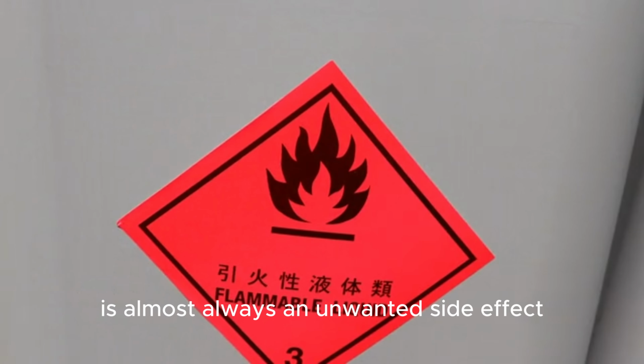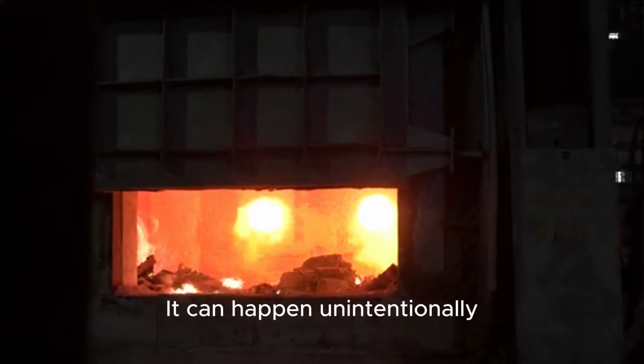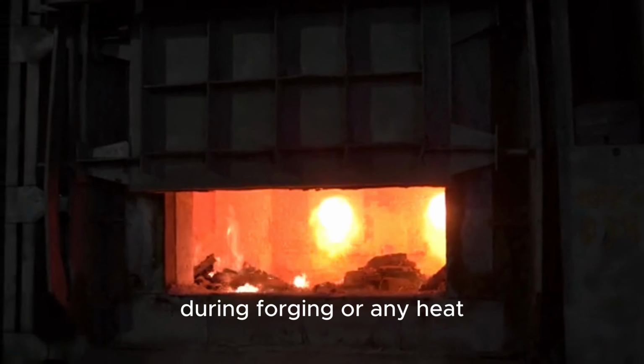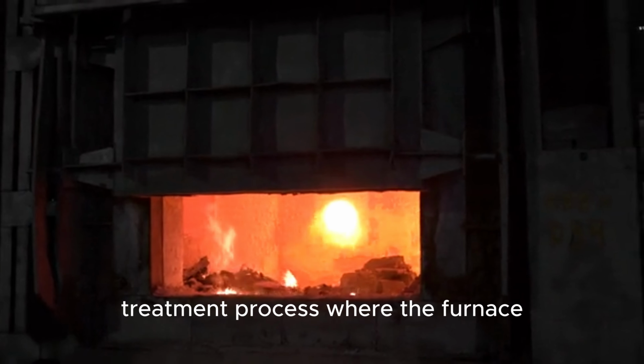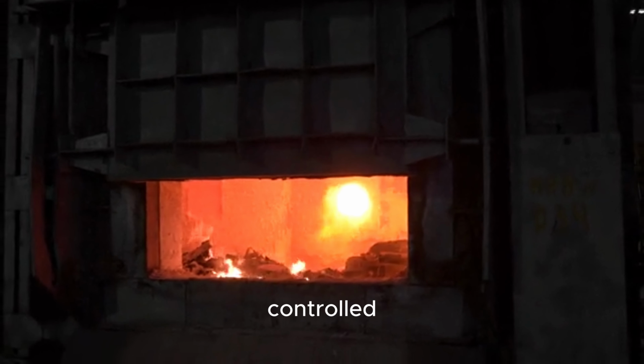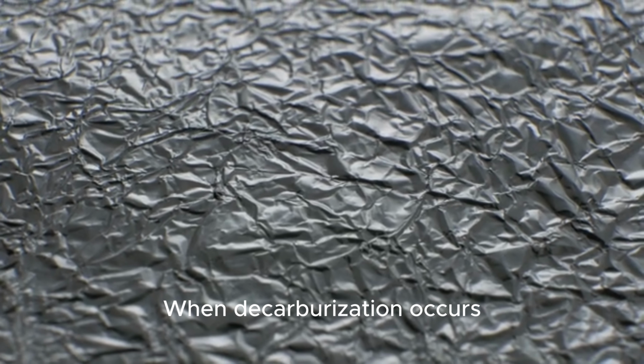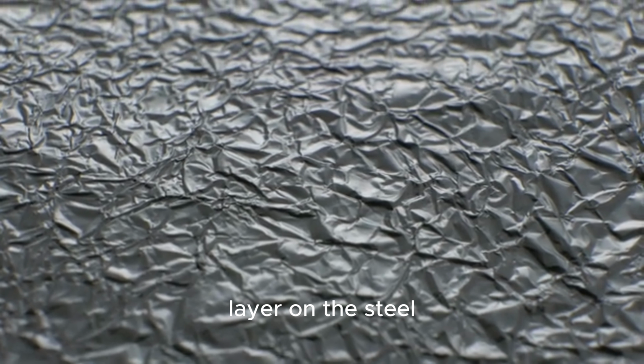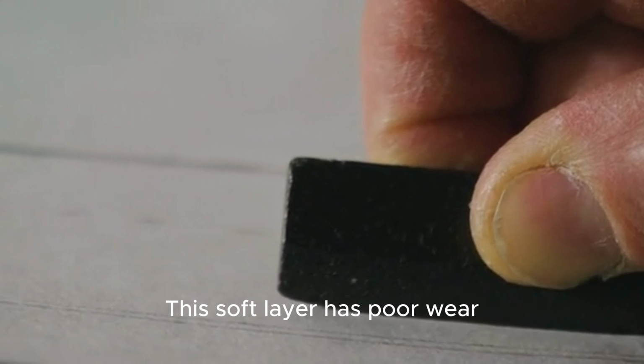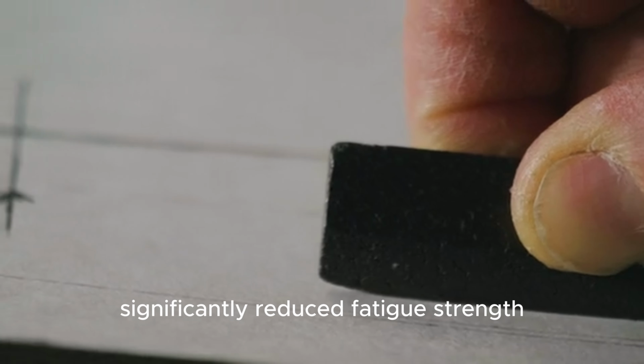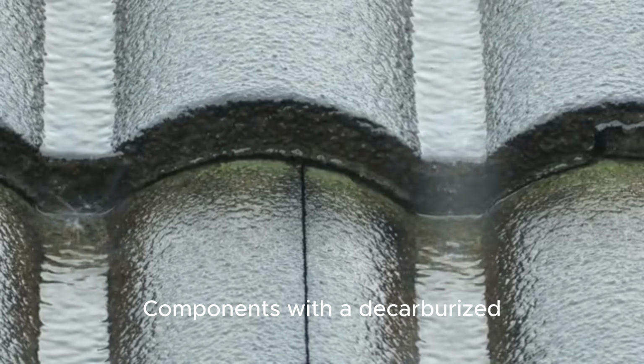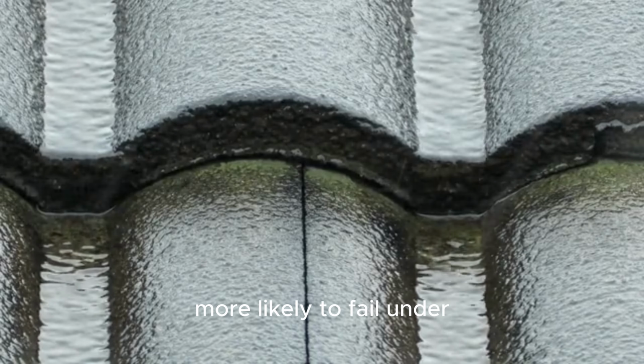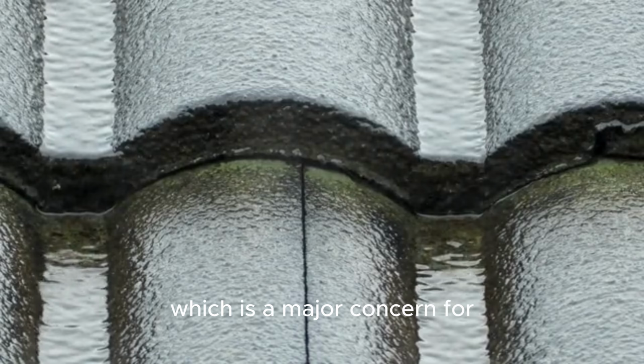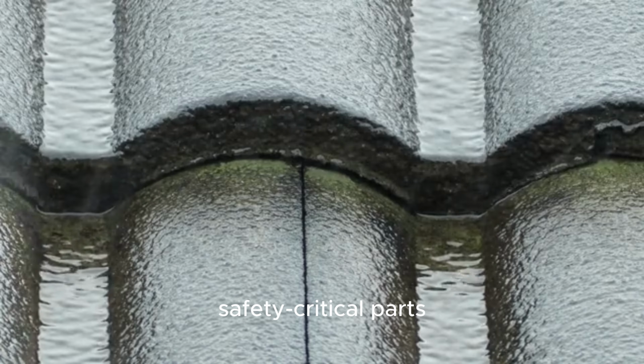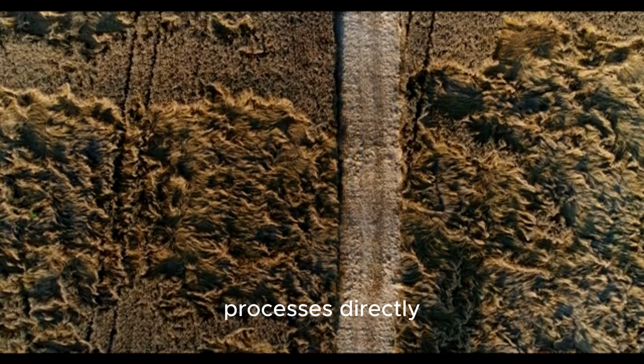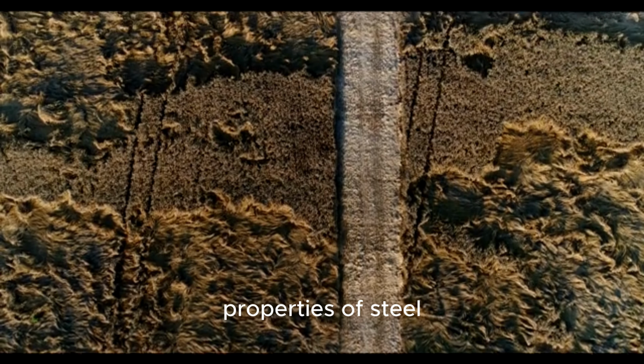Decarburization, however, is almost always an unwanted side effect. It can happen unintentionally during forging or any heat treatment process, where the furnace atmosphere is improperly controlled. When decarburization occurs, it creates a soft surface layer on the steel. This soft layer has poor wear resistance and, more dangerously, significantly reduced fatigue strength. Components with a decarburized surface are much more likely to fail under repeated stress, which is a major concern for safety-critical parts. Now, let's look at how these two processes directly impact the mechanical properties of steel.